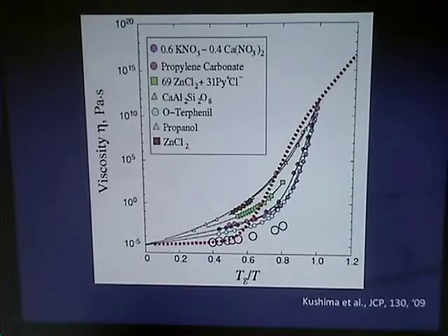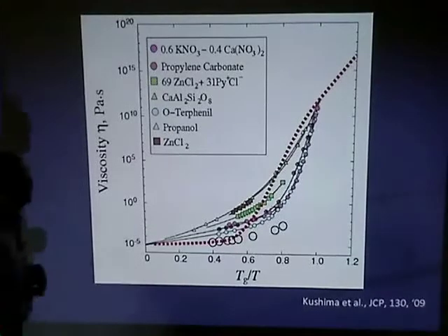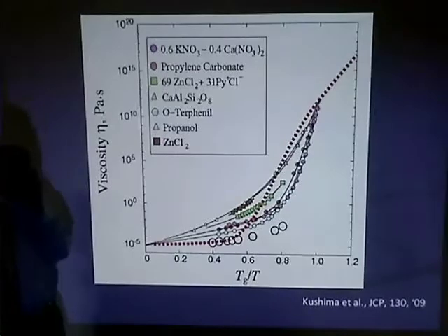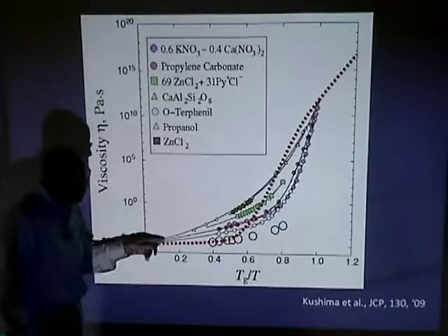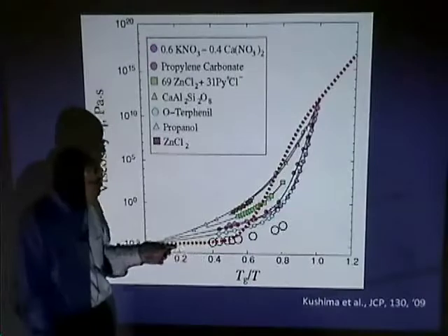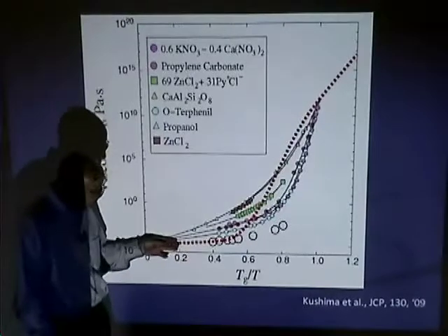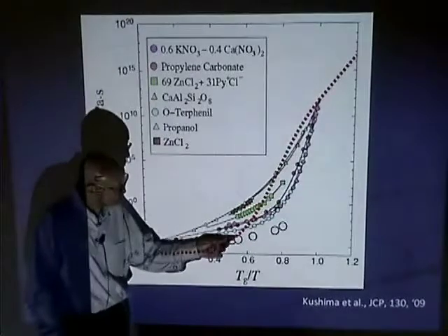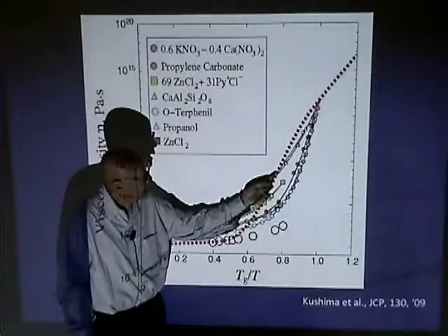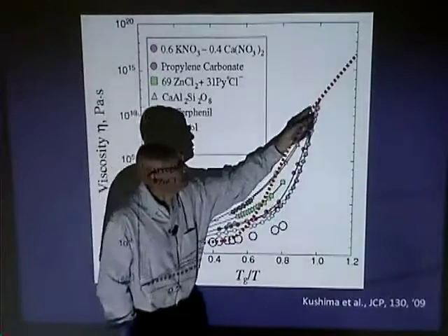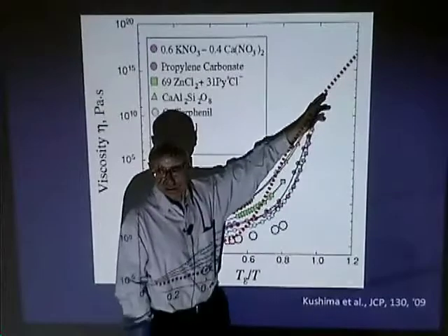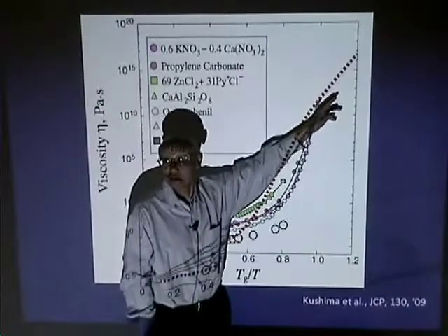I don't care which of these TGs you choose - somewhat below TG you get a more Arrhenius temperature dependence, so there seems to be a different temperature dependence in the glassy state. If I pick up what Jack is saying, considering this mostly Arrhenius, there's a transition from strong to fragile behavior, and then at some point close to TG there seems to be another transition back to strong.